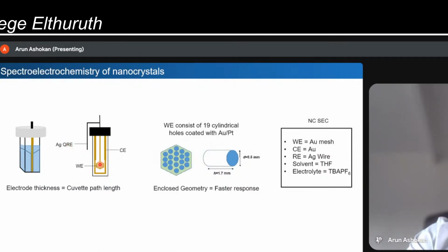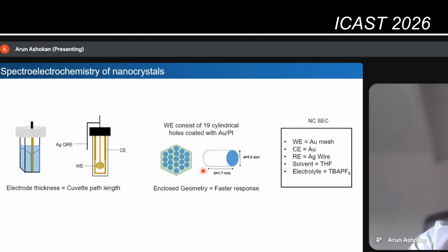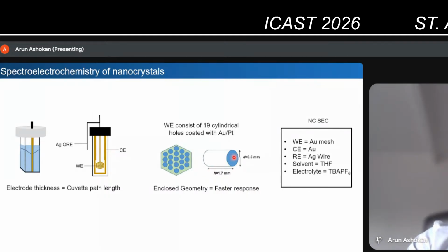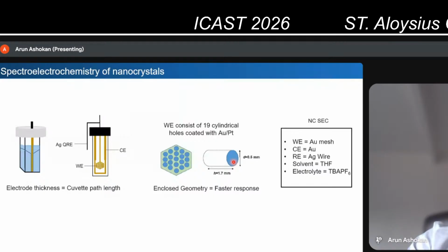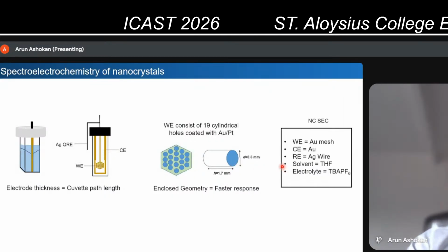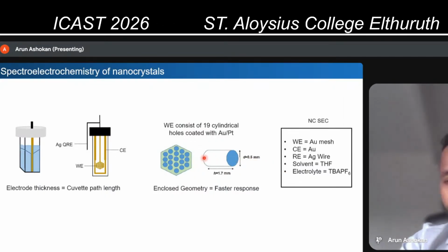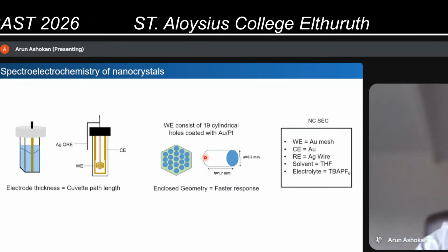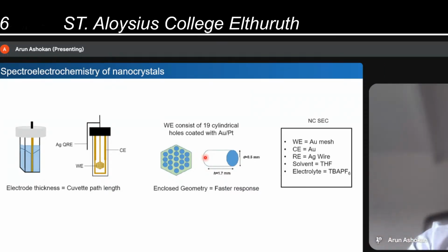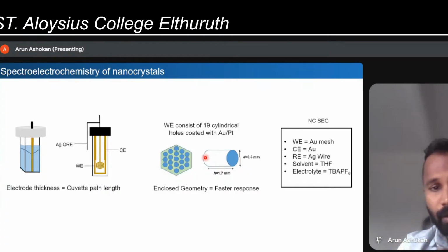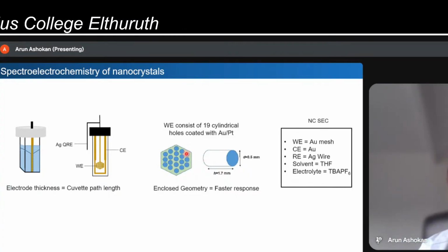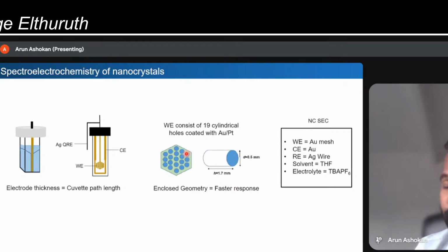If you closely look at the working electrode, it looks like a honeycomb. Basically, each of these holes is a cylinder in three dimensions. Your nanocrystals will diffuse and collide with the electrode surface and get charged. At the same time, we will shine light and collect the absorbance or scattering or whatever spectroscopic signals we want. This enclosed geometry of the electrode helps us get a faster response. We are doing all these experiments in solution, and it will be limited by diffusion. So if you have an enclosed geometry, more nanocrystals will be charged and you'll get a faster response.